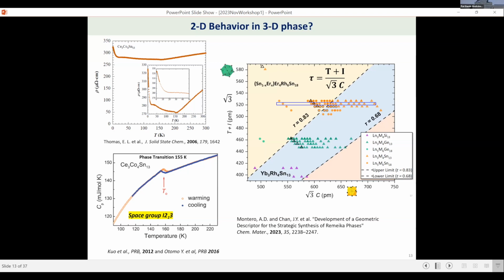but this is for the intermetallic. And another thing that was exciting to us is that depending on the lanthanides, whether it's cerium or ytterbium, we could predict which structure type should have formed. Because if it is ytterbium 2+, for instance, that would be a larger cation, looking at the bottom of the periodic table, lanthanide contraction. So we're able to predict which structure type should have formed. And most importantly, the oxidation state, just by looking at this map. And there's still some refinement to do with respect to what are the critical parameters, but that's ongoing.